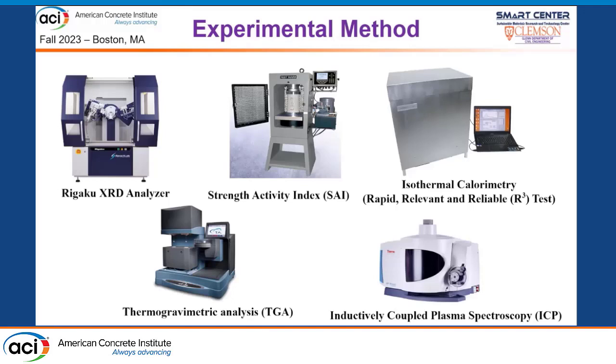We primarily use 5 different methods. The first one is to use X-ray diffraction to quantify the crystallinity or the amorphous level of the SCM we used in this study. Generally, the more amorphous area, the more amorphous content of the SCM, the more reactive the SCMs are.